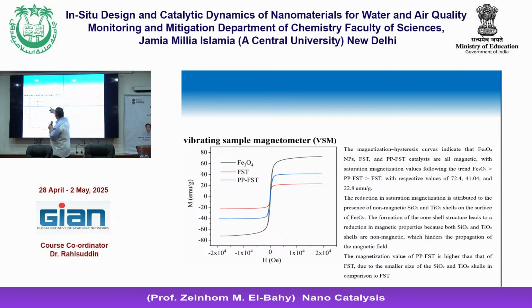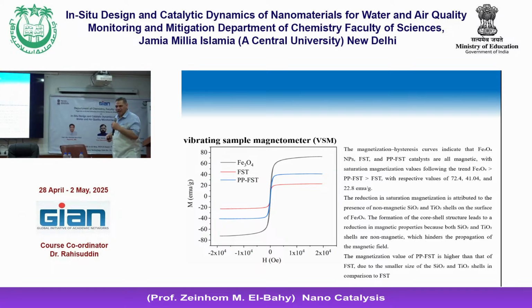It is much decreased. This means that it is shielded or something is around it, isolated from detection. The magnetic susceptibility decreased in both cases, meaning the magnetite has been shielded with a shell in both cases.